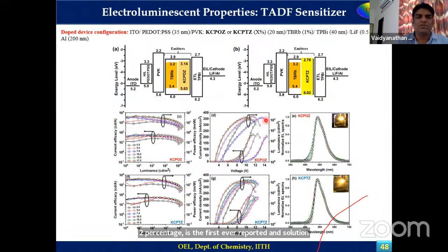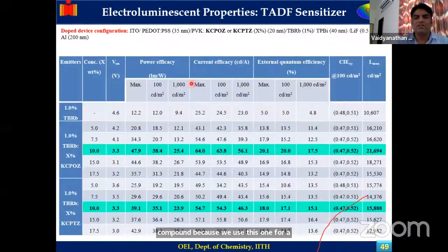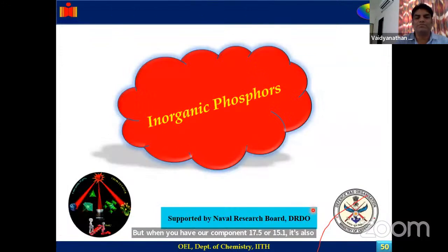Of course, we used this one with rubrene as a sensitizer. We found that without our compound it's 4.8, but when you have our compound, it's 17.5 or 15.1, which is also a good number. As a sensitizer, it can be used. So I completed the first part of my presentation.